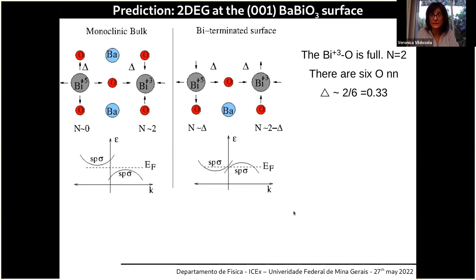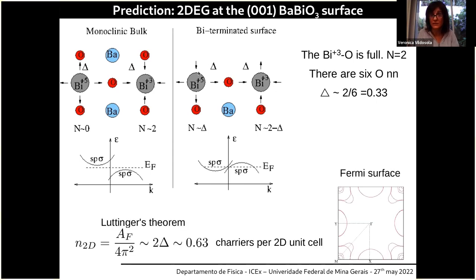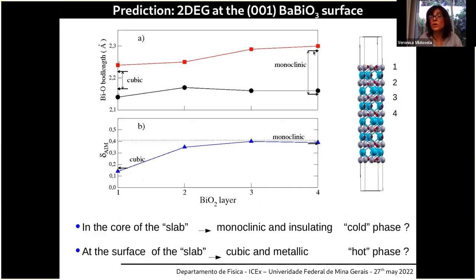We can prove this by doing realistic calculations of the Fermi surface of this system. And through the Luttinger theorem, we can estimate the 2D carrier density by calculating the area of the Fermi surface, that it is here, and dividing by 4 times pi squared, which, if we do the calculations, we obtain 0.63, which is very similar to this estimation of 0.66. What we are suggesting is that there is a new mechanism to generate two-dimensional electron gases at the surface of charge order semiconductors.